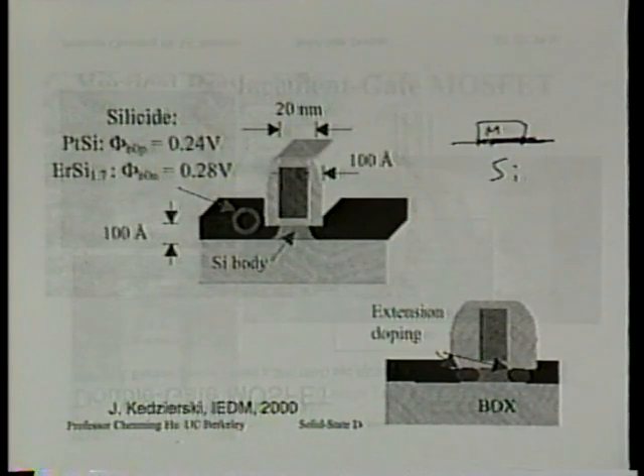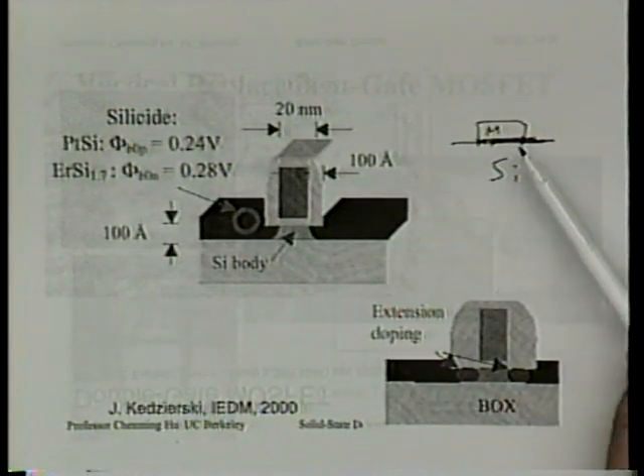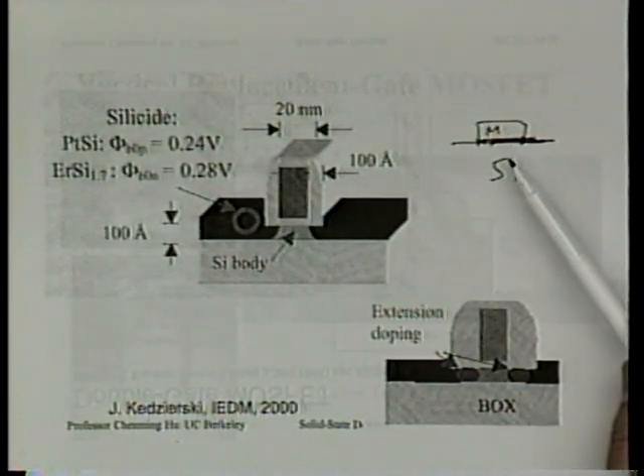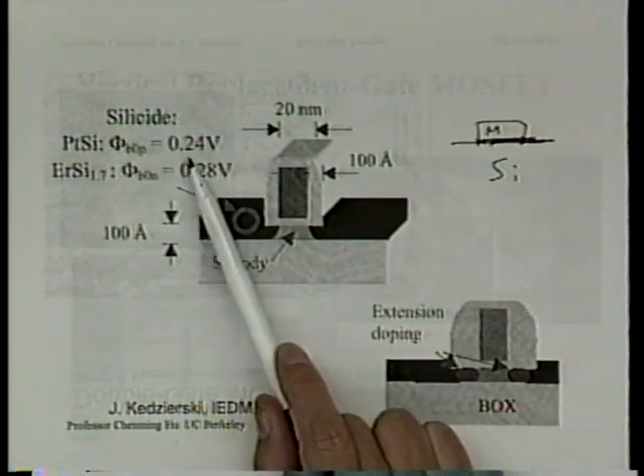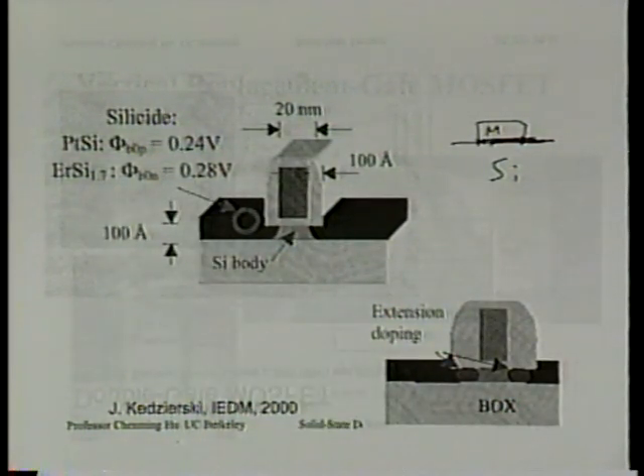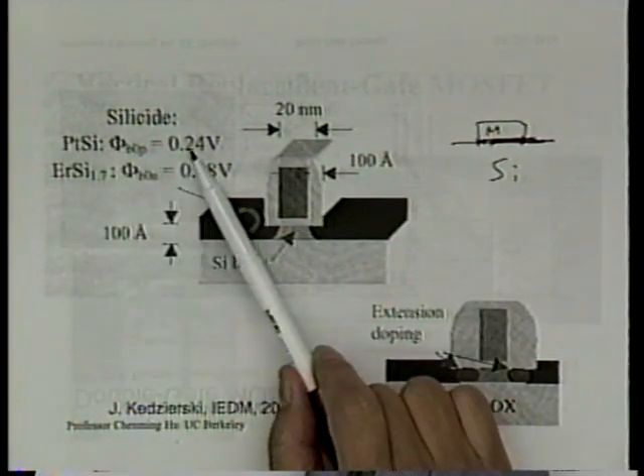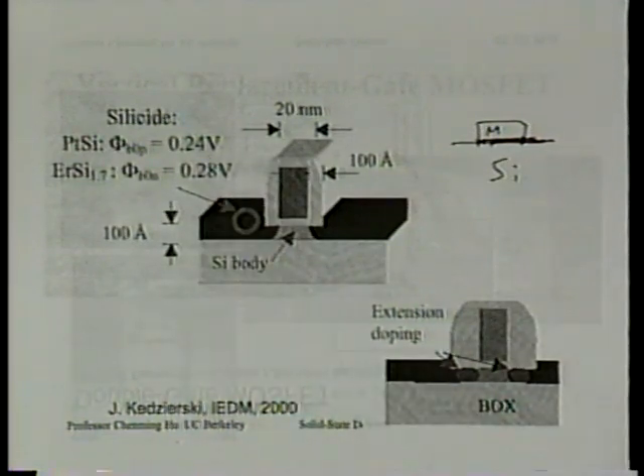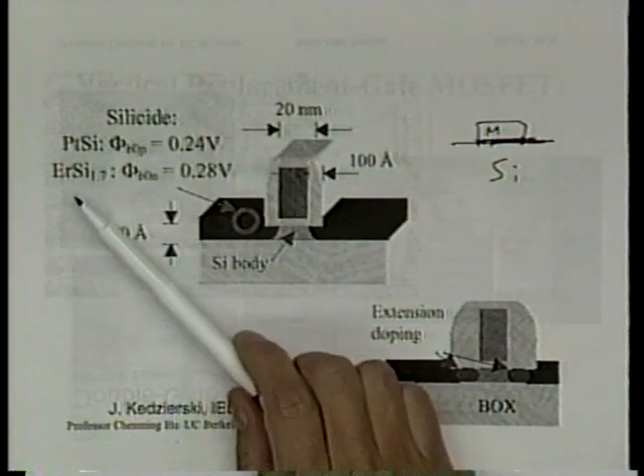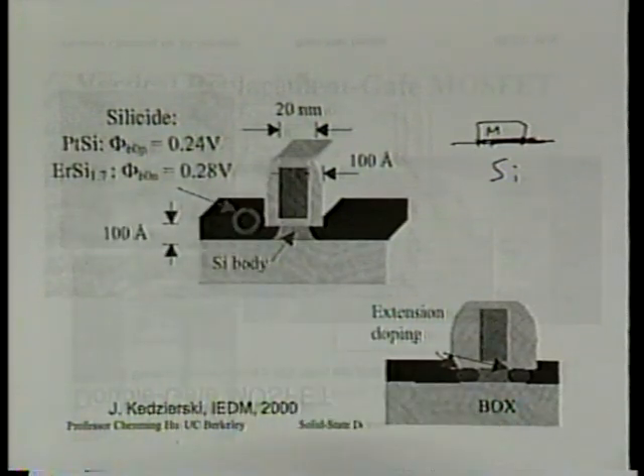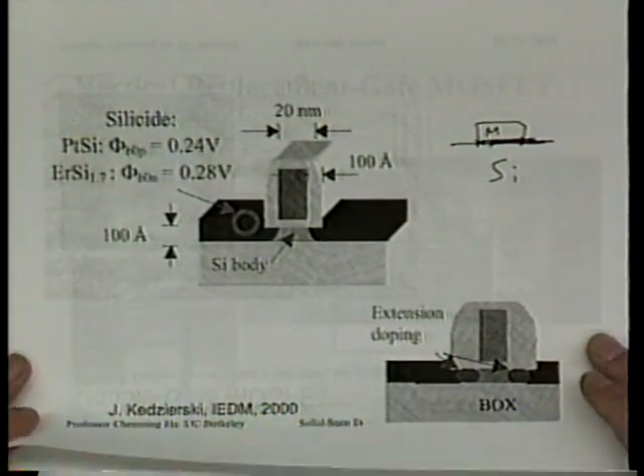All right? And the way to minimize interface resistance is to use a silicide silicon Schottky barrier that has very low barrier height. We believe it has to be less than 0.2, 0.22 eV. So for PMOS, platinum is not too bad. For NMOS, there is no good material. And Jacob's contribution was that he developed technology using erbium silicide that gives the best result. But even then, we still don't think it's very good, and more work has to be done on that. All right? But many companies are very interested in this and want to continue to develop that.